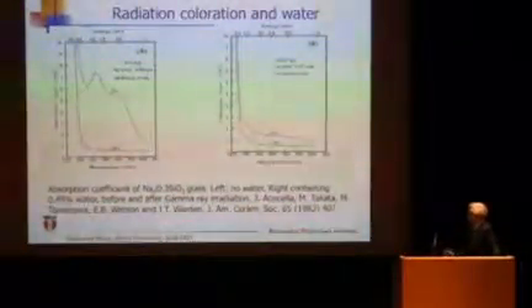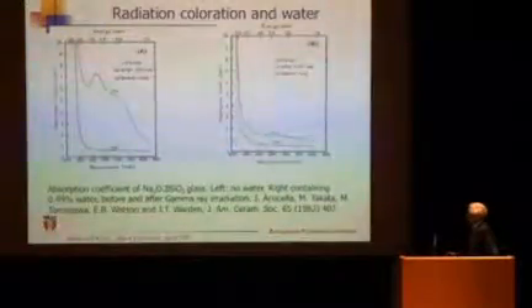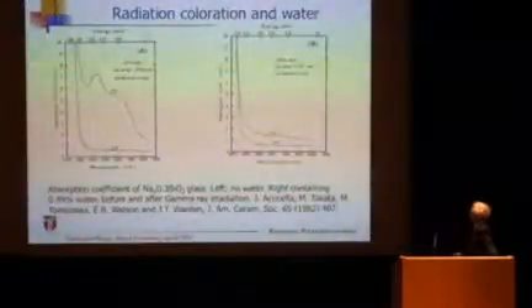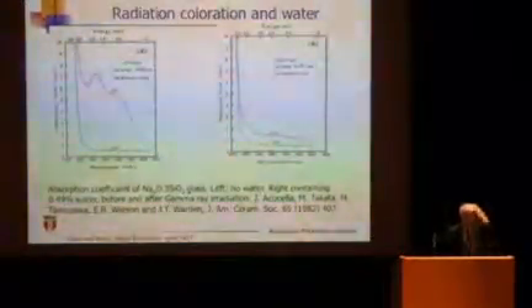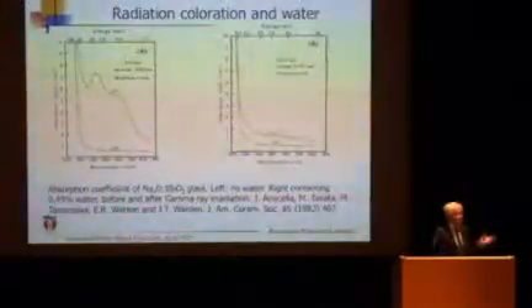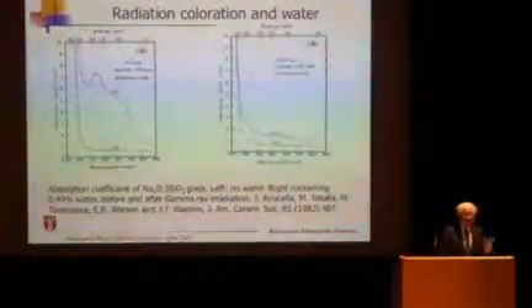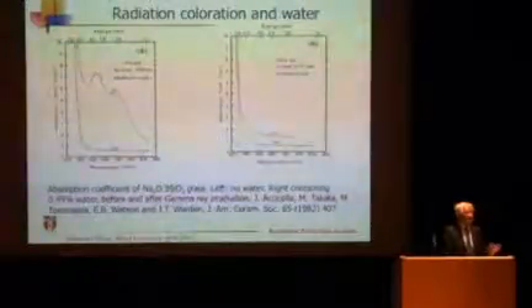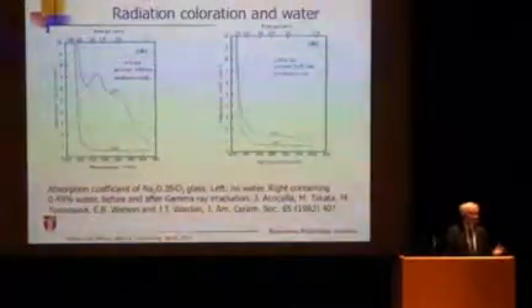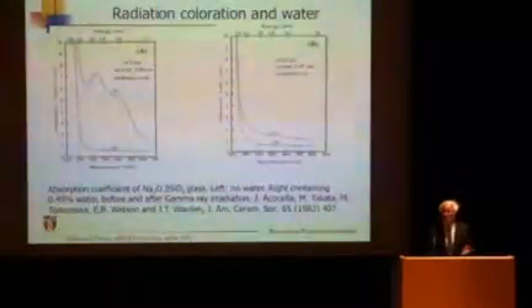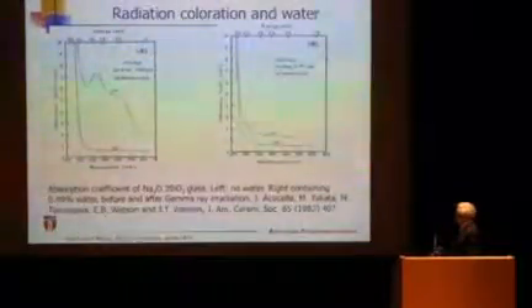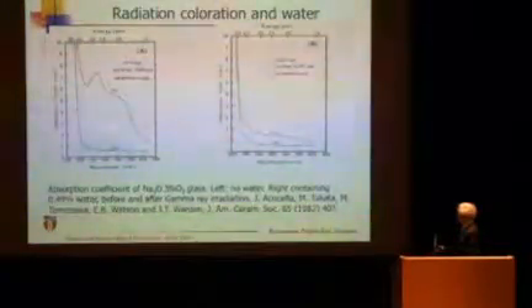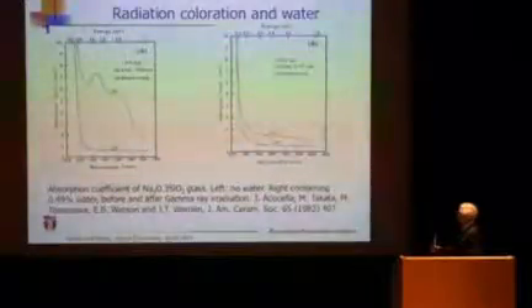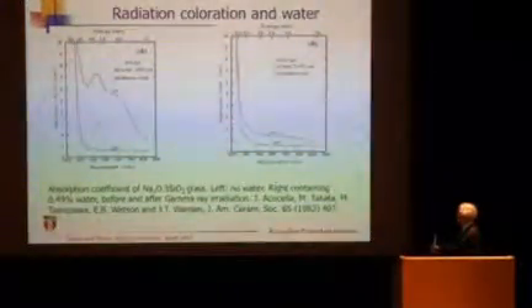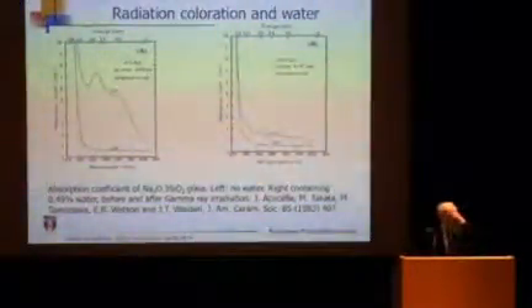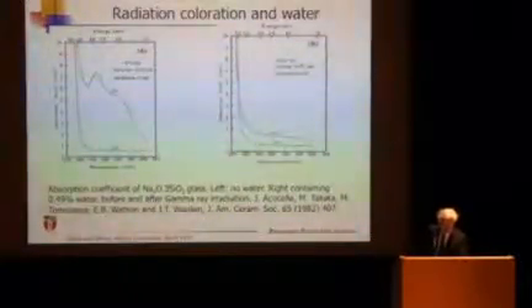We found also that when you expose glass containing water, the glass doesn't color. Normally, when you expose glass to high intensity X-ray or gamma ray, glass becomes dark brown or black. But we found that with water containing glass, the coloration is very small, while the glass without water has a tremendous change in color. It's shown in terms of spectroscopy.